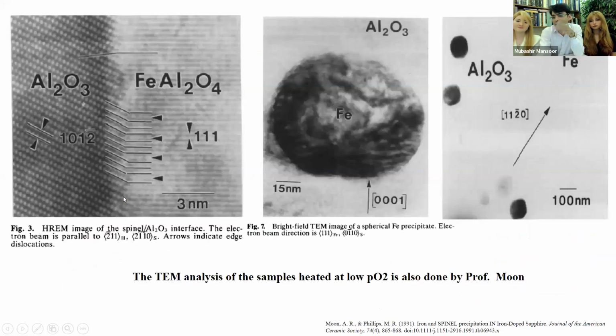Now, this is one example where we optimized by calculation. If you have, for example, a hypothetical case, 3,000 parts per million of iron and 2,000 parts per million of titanium, which conditions would create your solid solution? And if you have too little oxygen, if you're somewhere here, then we would expect precipitation of iron, and under transmission electron microscopes, we can actually see the iron.